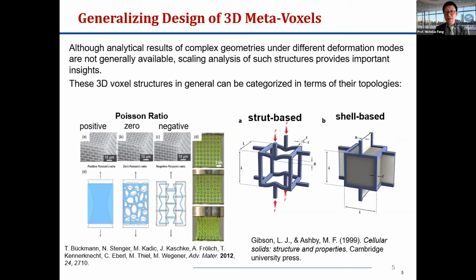It turns out those complex geometries sometimes are difficult to predict because there are different deformation modes that are embedded in those lattice structures. But scaling analysis actually helps us to outline some important trends and offer insight of how such structures can be inversely designed. Generally speaking, we are looking at two important topologies, truss-based elements or beam elements, as well as the thin shells. For example, for the case of closed forms, we are really looking at how the shell layer bends and stretches under different loading.